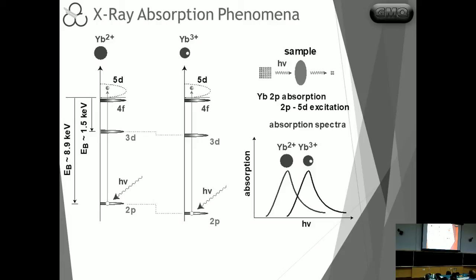When we reach an energy of around 8.9 to 9 kilo electron volts, then we enter a resonant condition, for example, for this 2p state, which excites these electrons up into the conduction band. And so one way that we can do these measurements is doing the resonant X-ray absorption, as we see these electrons absorb the synchrotron radiation.